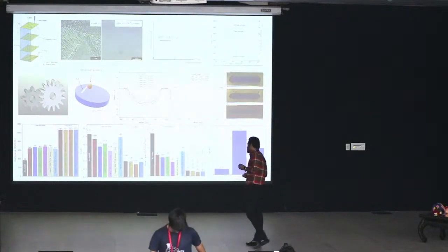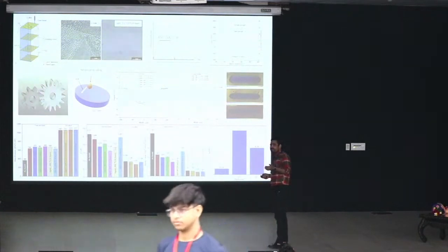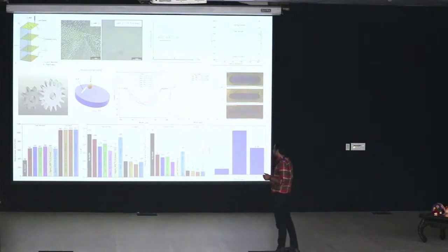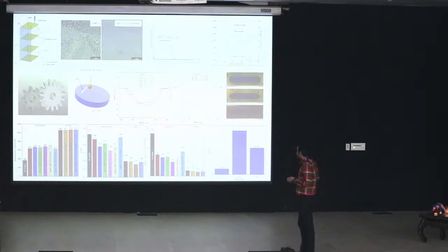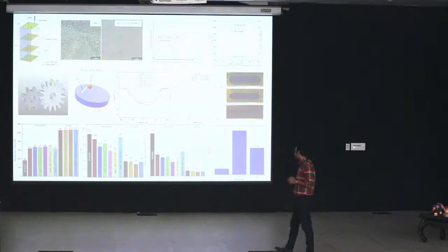But after aging, we find that for the aged specimen, the coefficient of friction as compared to the as-built specimen is reduced by an amount of 30%. And after nitriding, this decrement in the coefficient of friction is by an amount of nearly 50%. And similarly, the wear rate of the aged specimen is reduced by an amount of 60%. That is a big number as compared to the as-built specimen. And after nitriding, it is further reduced by an amount of 90% as compared to the as-built specimen.